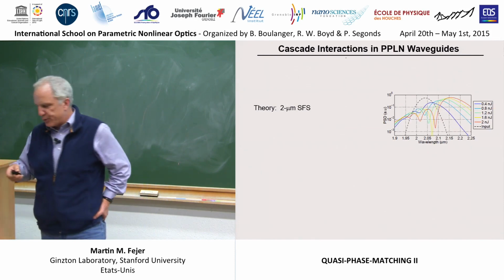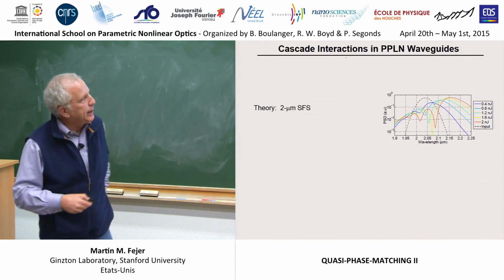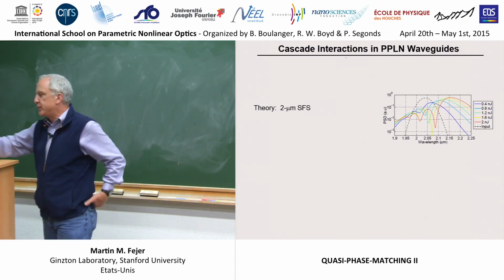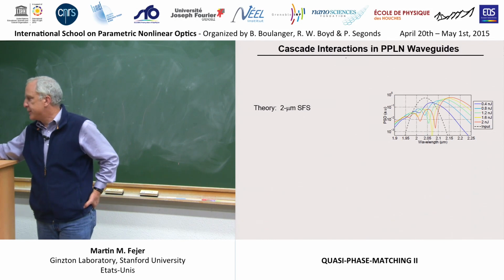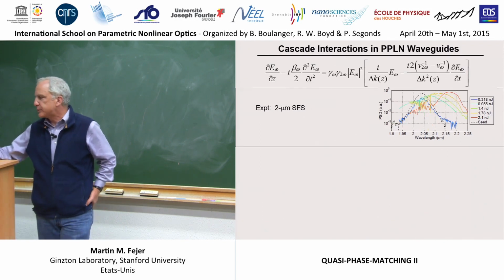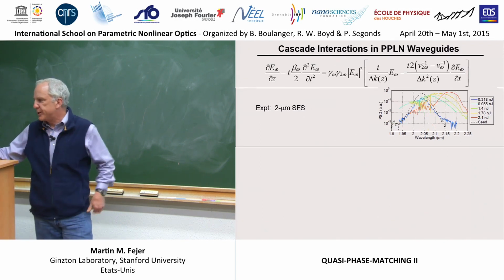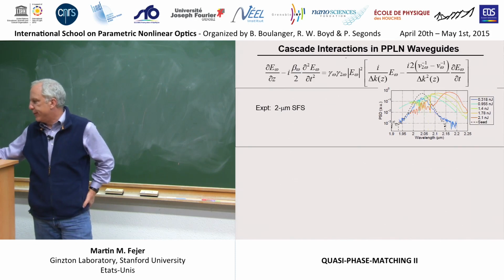And if you compare it to the experiment based on this cascading, you see that this Raman self-frequency shift term very closely predicts what you see in the real system. Those aren't too bad agreement.